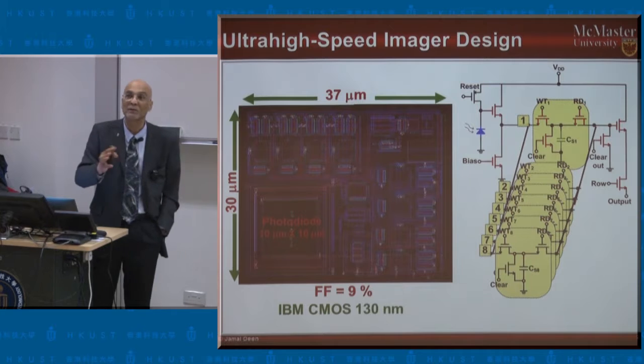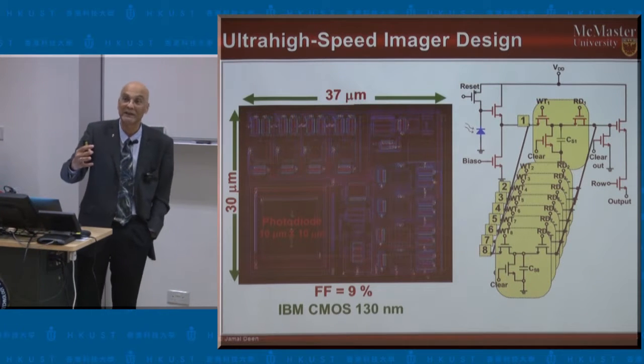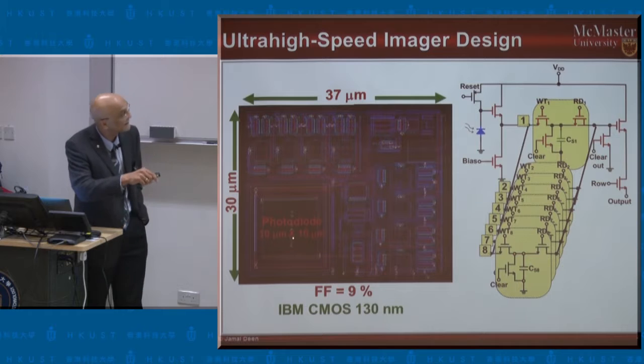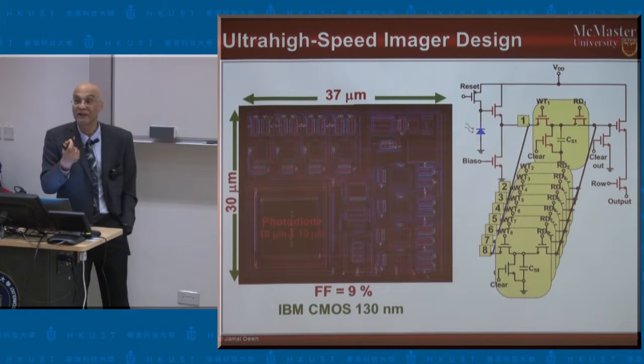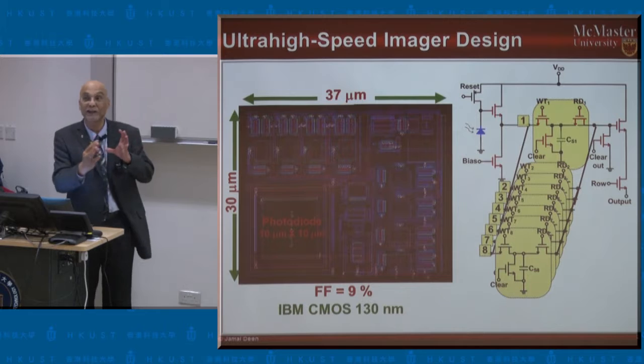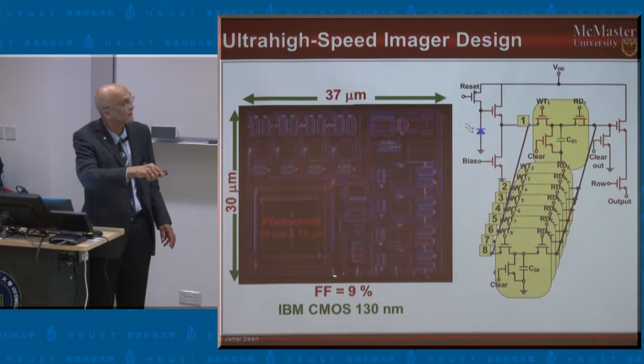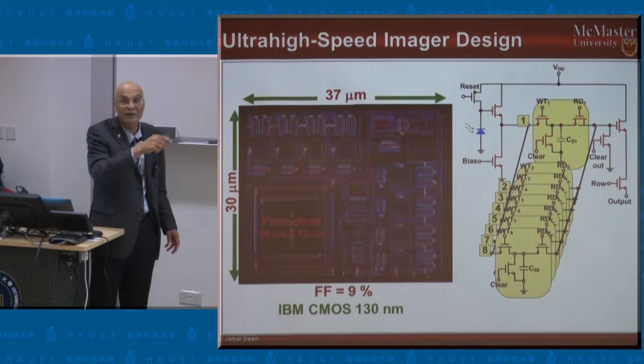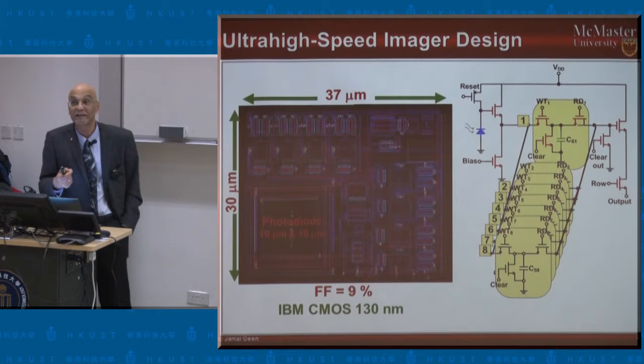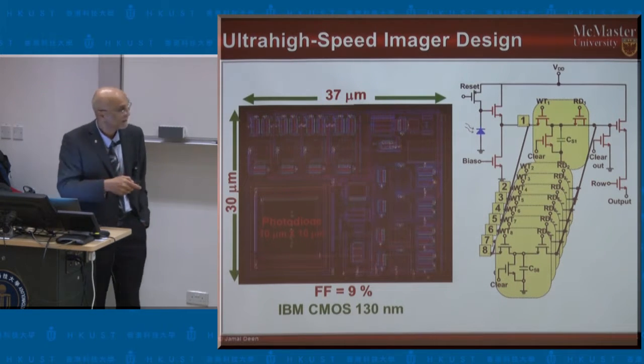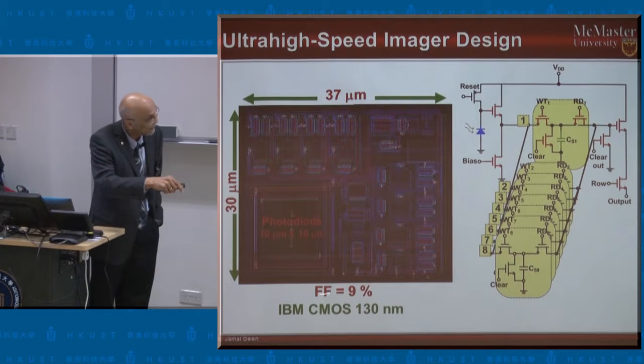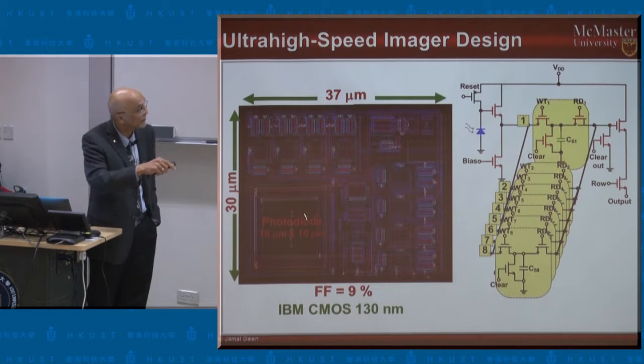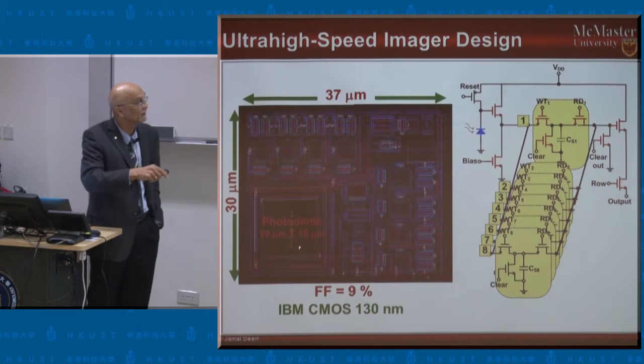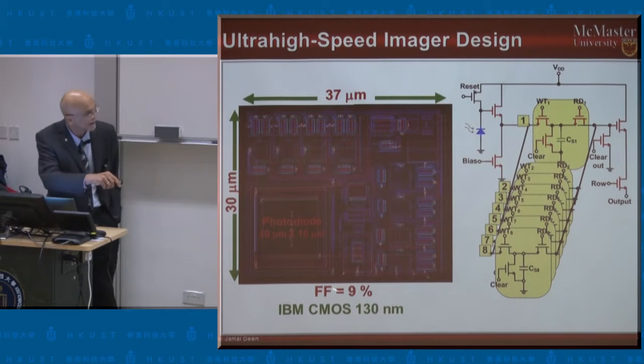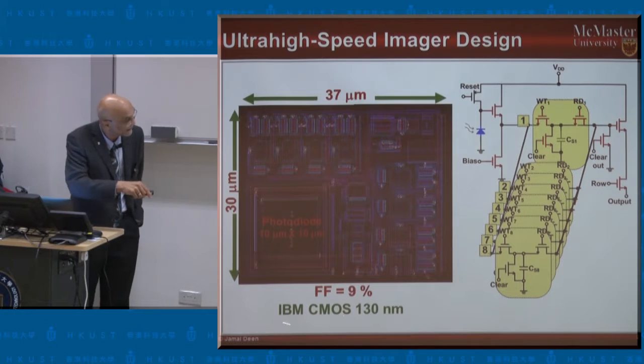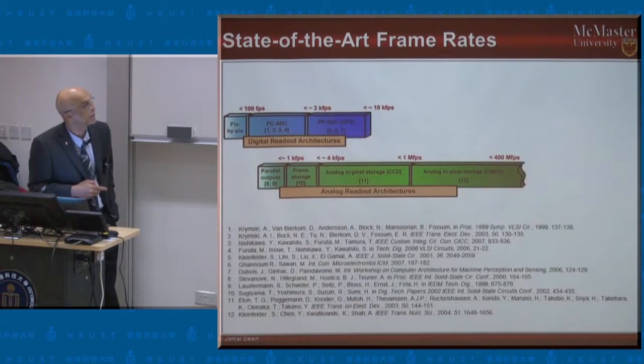Of course, there's always a compromise when you make some advance in one area. The compromise that we're making in this case is that the size of the imaging element, so this photodetector, actually shrinks relative to the size of the pixel to accommodate all the extra electronics you're going to add to improve the speed of image acquisition. So we change from a higher fill factor, and fill factor is just a measure of the area of the photodetector to the size of the pixel, to a relatively modest fill factor of around 10%. And this is the design that was done in 130 nanometers a few years ago.